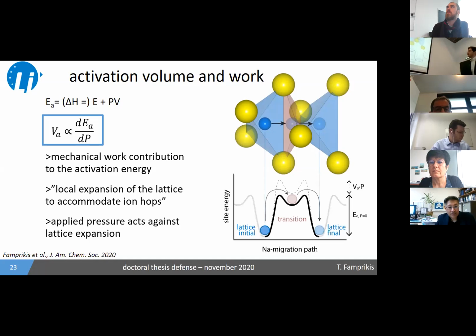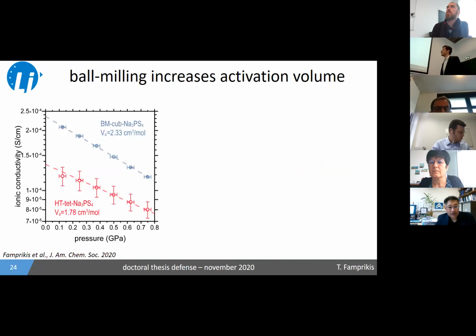And to link with the picture before, basically what's going to happen is as I apply pressure, this is going to increase the activation energy that I need to overcome in order to get into the transition site and complete the hop. So if we plot our data as I showed before, you get the straight lines that I described, and you can derive from the gradients the activation volumes. You see very quickly that there is quite a large difference in activation volume between the solid state synthesized sample and the mechanochemically synthesized sample.